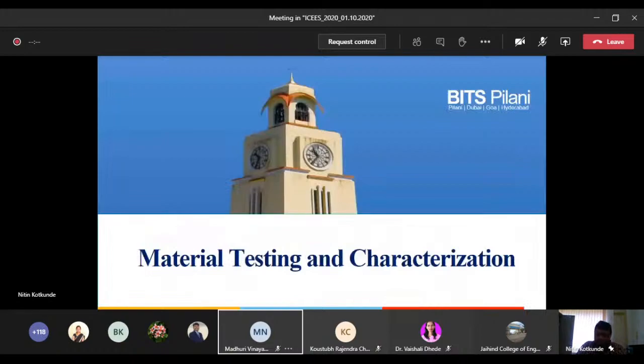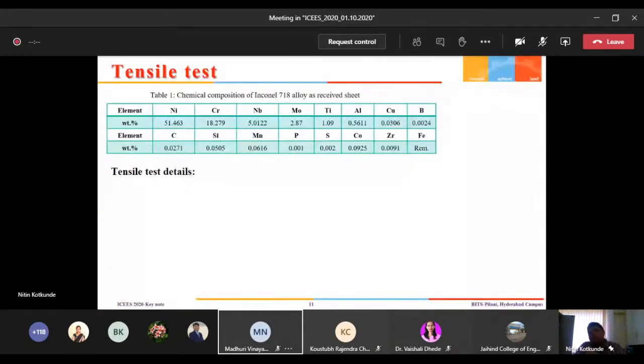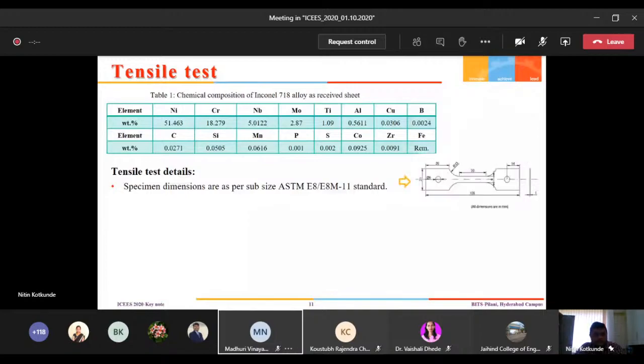So, material testing and characterization. Obviously, the very popularly used uniaxial tensile test is used to do the tensile test at different temperatures. The material is very costly, so we usually prefer the sub-size ASTM standard specimen, which is exactly a 50% reduction of the original one. This is a schematic of a dog bone tensile test specimen of a thin sheet of 1 millimeter thickness. These specimens are used to test the material properties at different orientations.